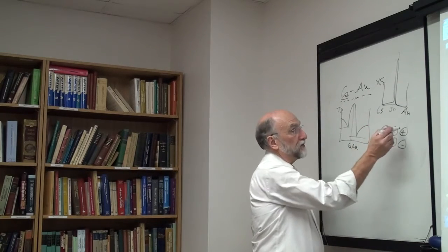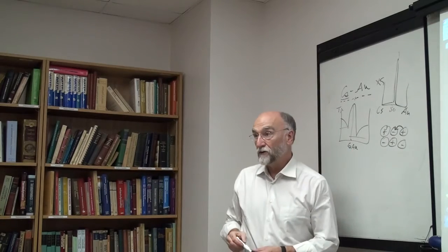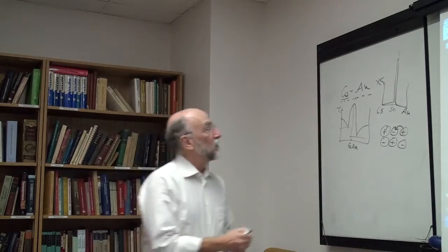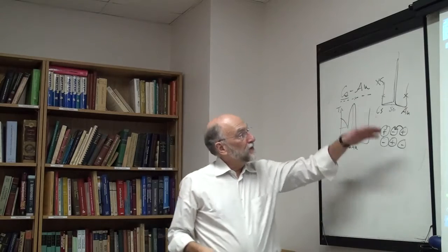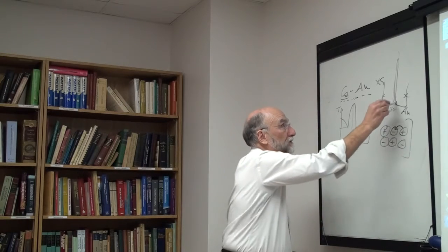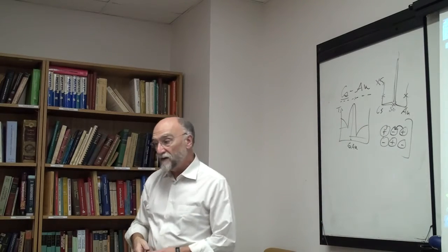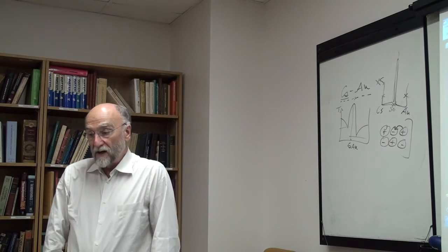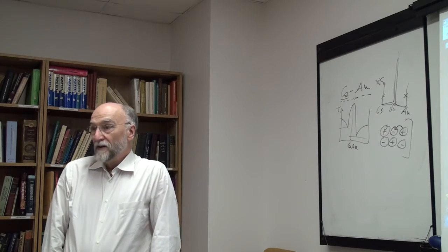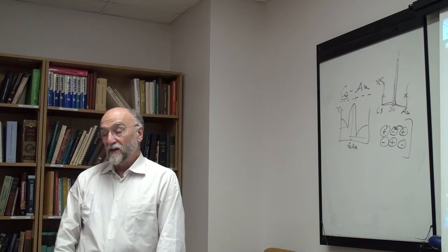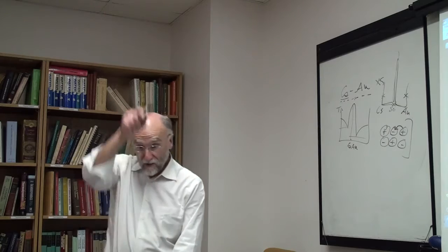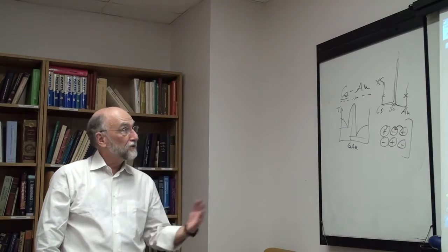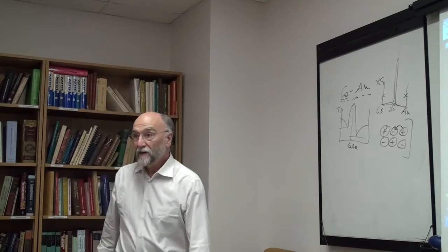And what's happened is the cesium has given its electrons over to the gold to make it basically an ionic material, even though the two ends over here are metallic. And it's completely miscible. Now this is interesting because if you look at the liquid at exactly 50-50, it's not an electronic conductor, it's an ionic conductor. It's translucent, not a metal, it's light blue I believe, and you can see through it. The conductivity goes way, way down. Electronic conductivity goes down to 0, becomes an ionic solution, basically.